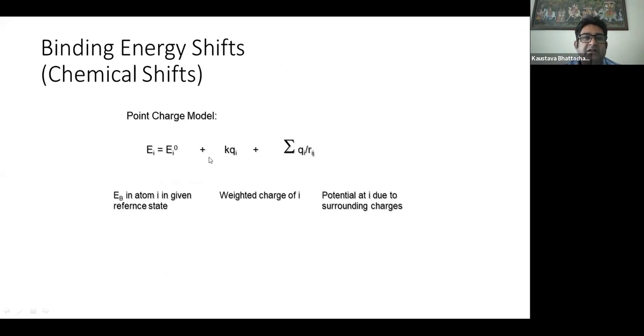So the binding energy chemical shifts will basically depend upon the electrostatic point charge model. It will depend initially upon the charge of the atom or the charge of the nucleus with which the reference is there, then the charge of the particular ion or the particular weighted charge of the particular electron, and equivalently it will also depend upon the potential field applied on that particular ionic charge or the electron surrounding that charge. So all three of these together will lead to the calculation of the binding energy as a sum of them.